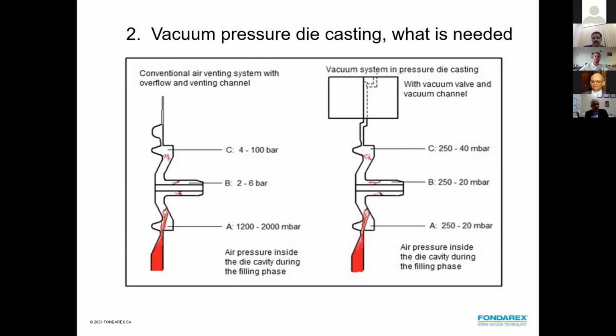And in the very best case, maybe down to 20 millibars. So the less gas we have inside the cavity, air is a gas, or let's say the less hydrogen from water, the better the filling is, and the fewer the alloy particles get involved with the metal. Therefore, at the very end of filling, we may still face 250 millibars. So compared to 4 or 1 or 10 bars, this is a very high difference.